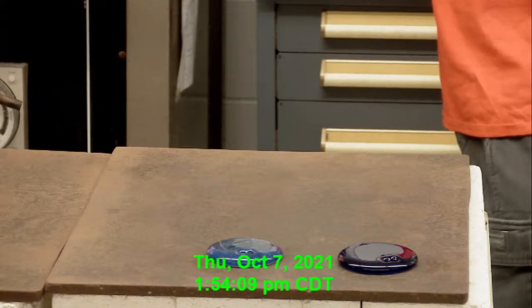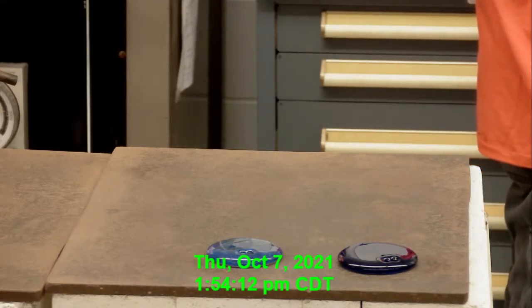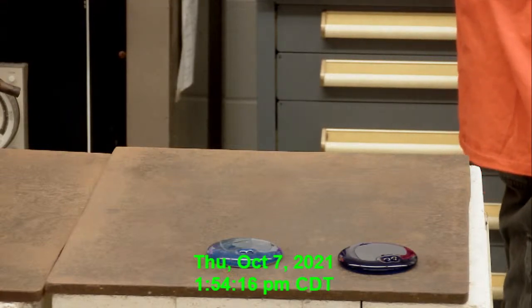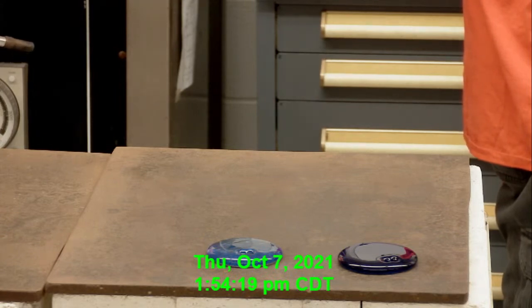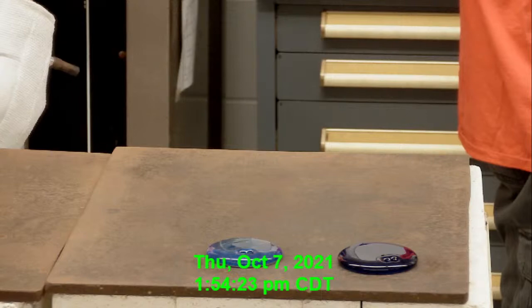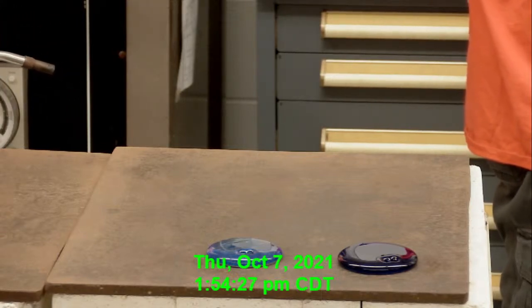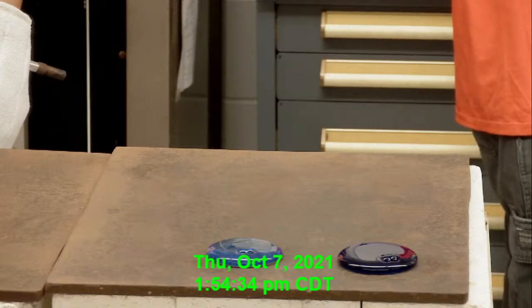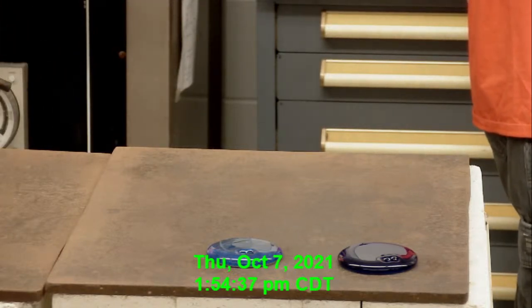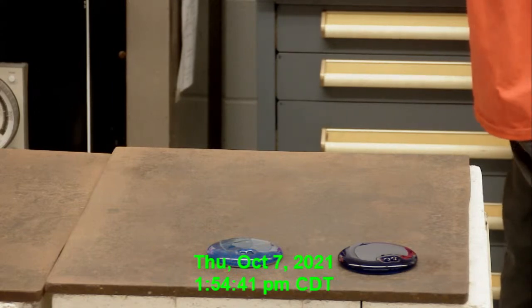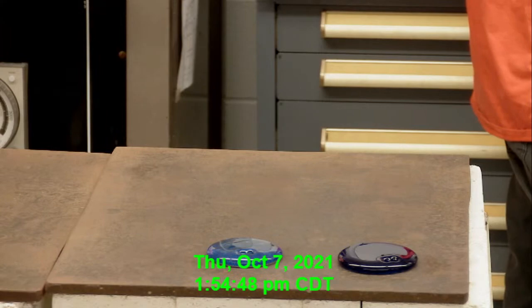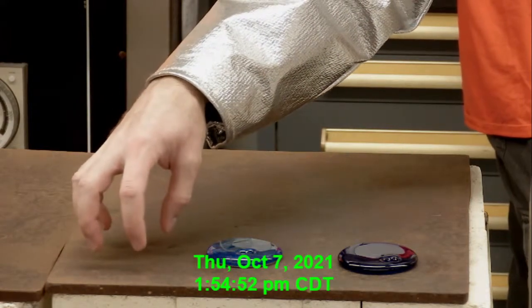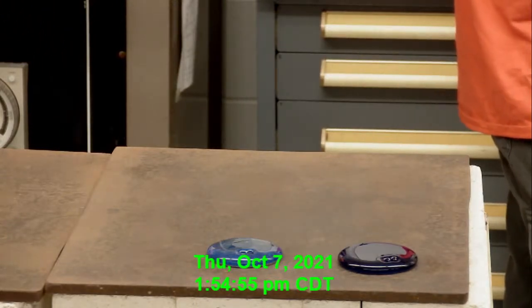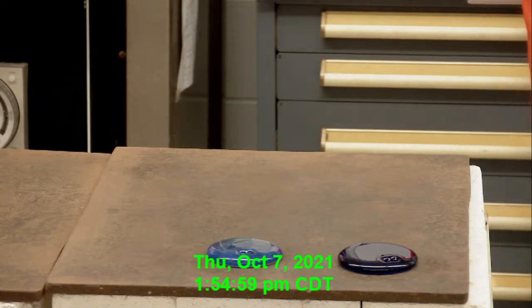All right, next up, we've got N1. This is, I guess, mostly Fisher purified silica with some white sand and some mason sand. So this is a mix of silica sources. That mason sand has iron in it that will make the glass turn a little bit greenish in color. We then have sodium carbonate washing soda, crushed limestone as our calcium source, more iron, plus 0.4 grams of copper oxide. So this will have probably some blue plus some greenish tint from the iron. That's what we're expecting. So we'll put that one right here. Is it N1? This is N1. N1. All right, so going from the middle.